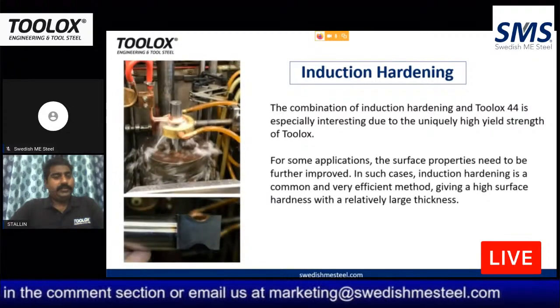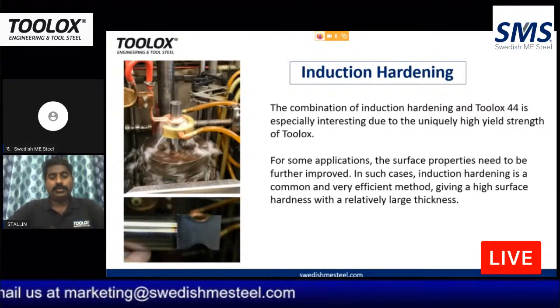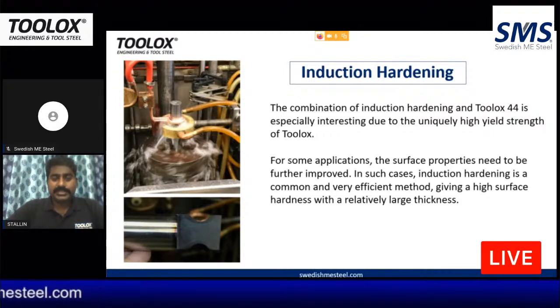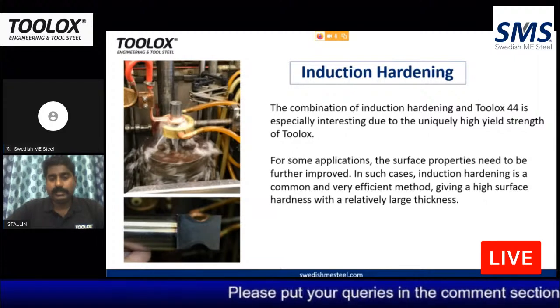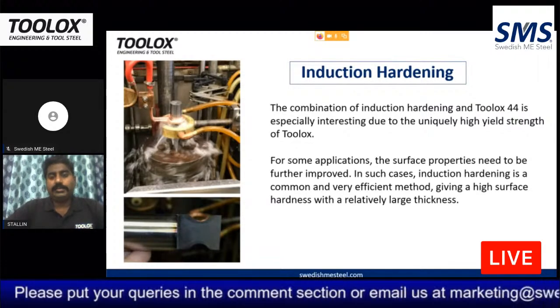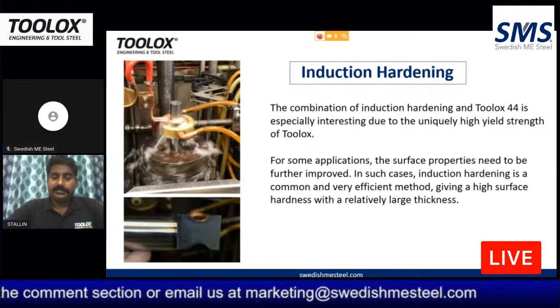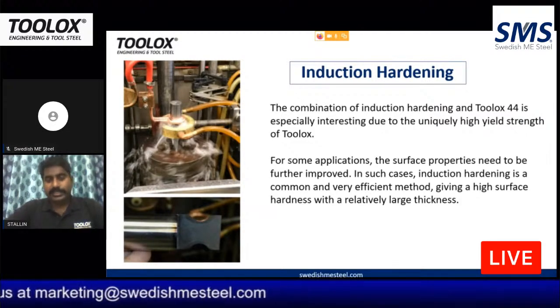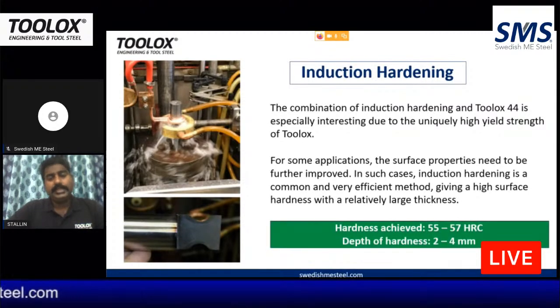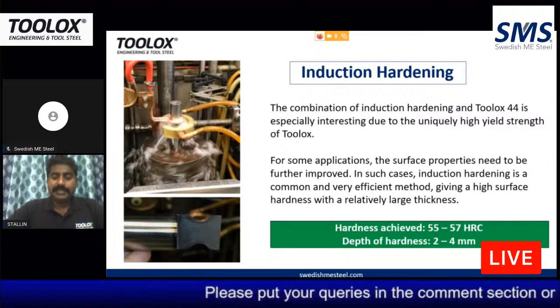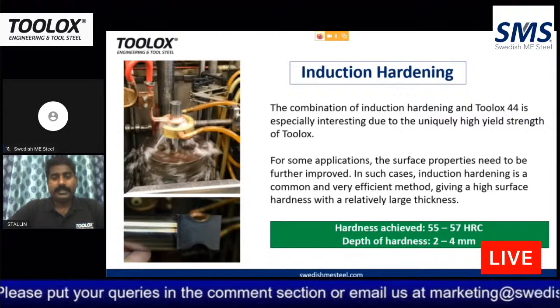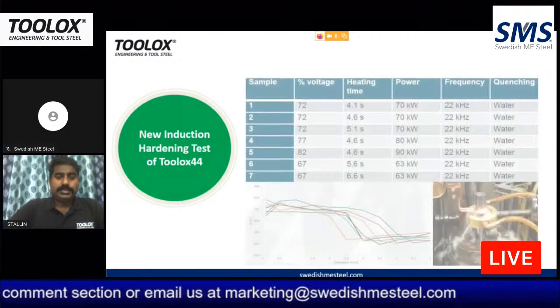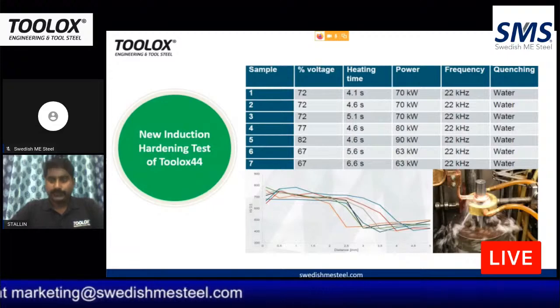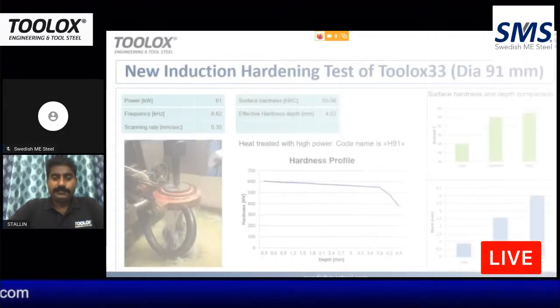And adding to that, induction hardening is also done in combination with Toolox 44. It is especially interesting because you can see the yield strength of the material is pretty high. So wherever you feel that the application requires better case depth, you can use induction hardening. If you do induction hardening, the hardness achieved would be anywhere in the range of 55 to 57 HRC, and the case depth will be around 2 to 4 mm. These are the various parameters used in induction hardening for Toolox 44, water quenching being the mode.